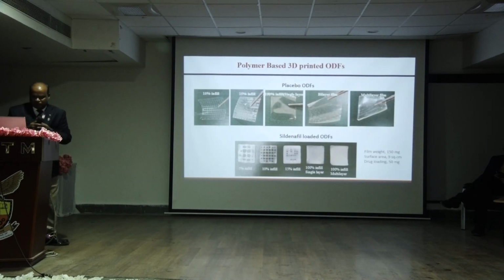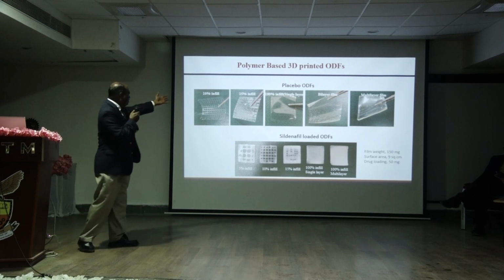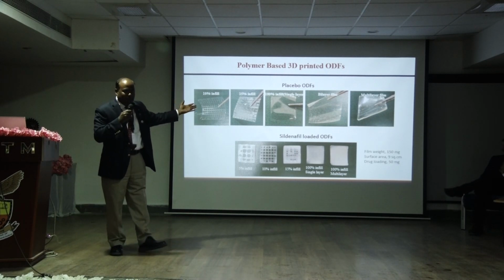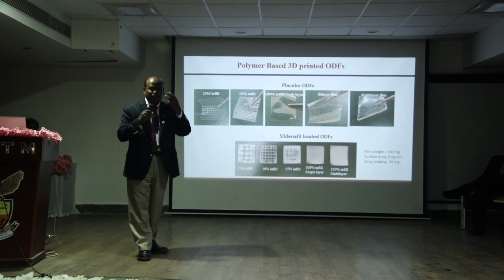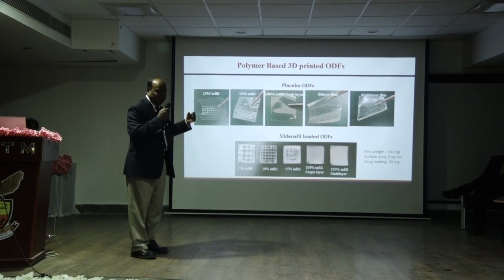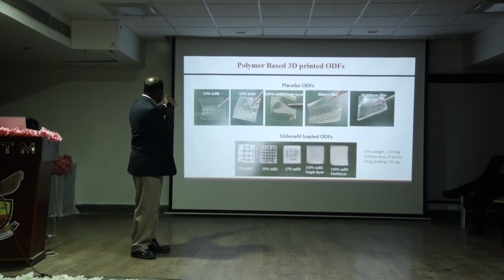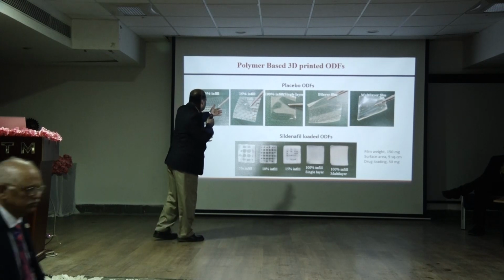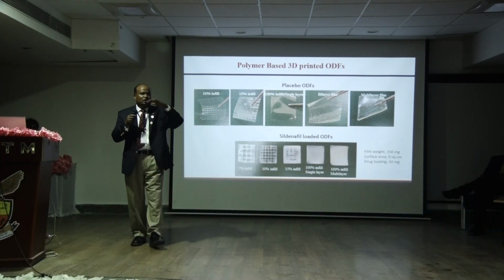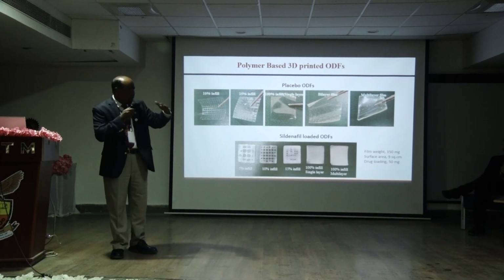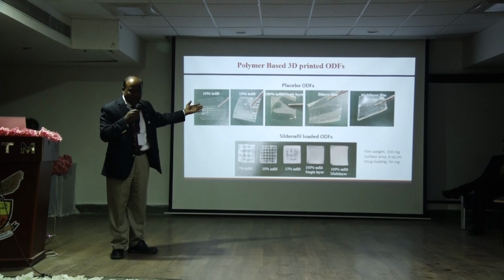Then, as you can see, we made the placebo films using pullulan as the polymer. Pullulan, water, propylene glycol. There are only 3 ingredients here, the placebo films. You got different infill densities to introduce the porosity. And then you got monolayer film and bilayer film and multi-layer film, as you can see from the picture.